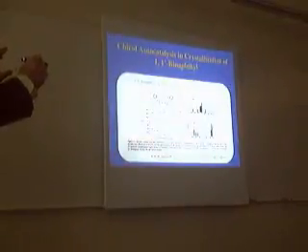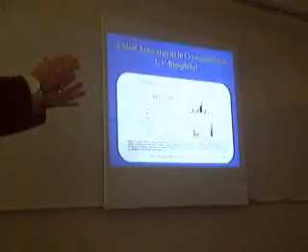And once you obtain chiral crystal, maybe at around 150 degrees, and you decrease the temperature below 145 degrees, it is kinetically stable, because the solid to solid transition is kinetically very difficult, and so that's why you get chiral crystal.